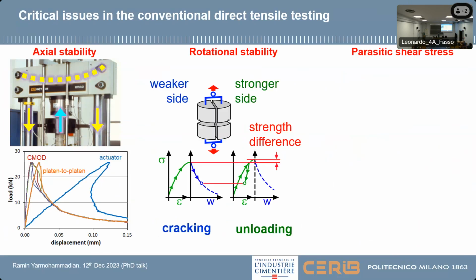And then the other issue is rotational stability in conventional direct tensile test. So usually, as you know, concrete is not homogeneous. Mostly we have a weaker side and a stronger side. When we are pulling, the side which is weaker is going to reach the peak, and the crack starts from one side. And then after that, you are cracking on one side and you're unloading on the other side. So you're going to get a mixed behavior of cracking and unloading, without getting the real behavior.